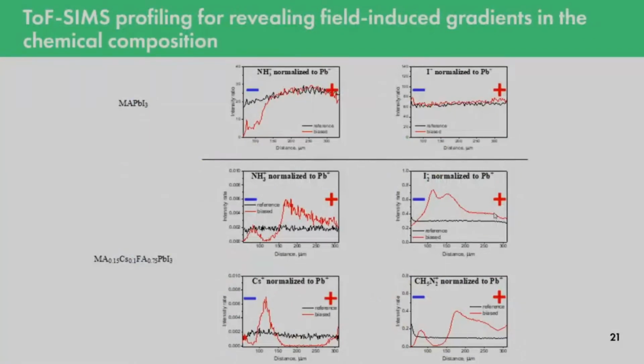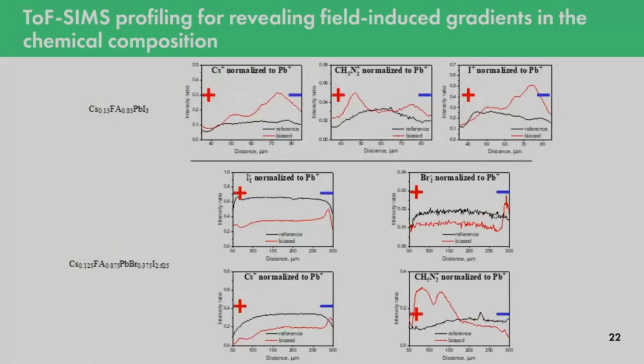We also decided to provide TOF-SIMS measurements for those materials, and you can see that methylammonium-containing perovskites all demonstrate the strong depletion of the organic part along the cathode. We already discussed this for methylammonium lead iodide, and here you can see the multi-cation structure methylammonium cesium formamidinium lead iodide, also with strong depletion of organic cations. If we look at methylammonium-free materials, the situation is mostly better, especially, once again, for cesium formamidinium lead iodide, which demonstrates the best performance for now in all current experiments. The depletion of the organic part is, of course, still present, but it's not so strong.